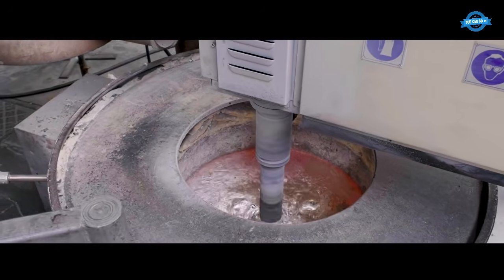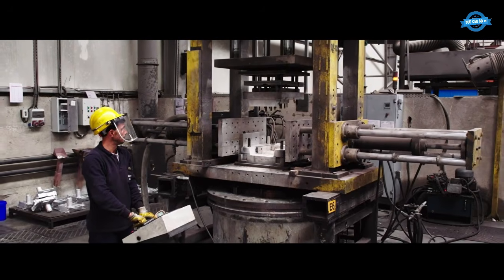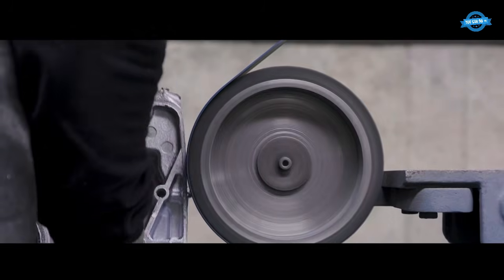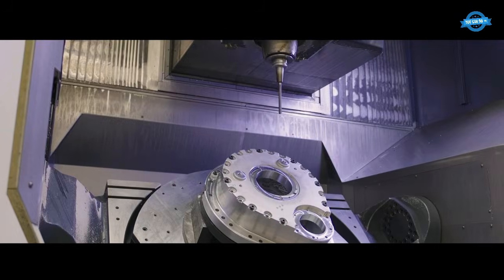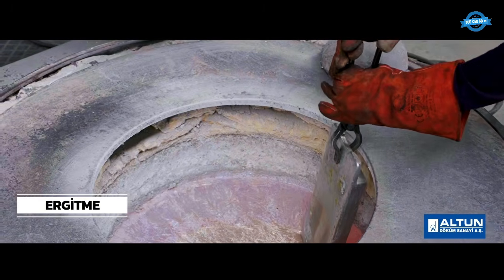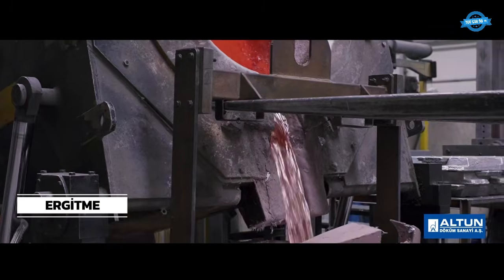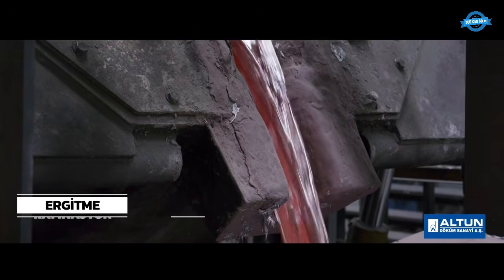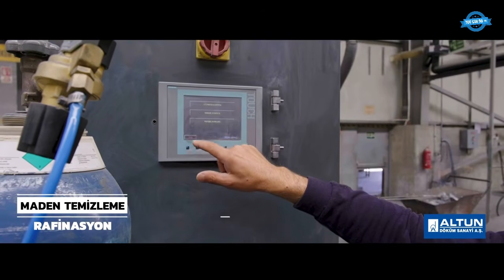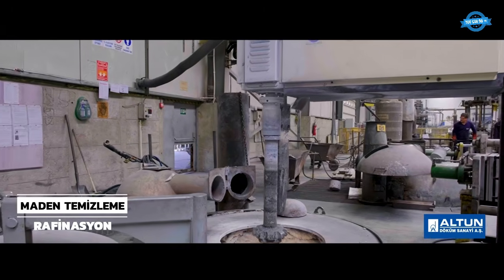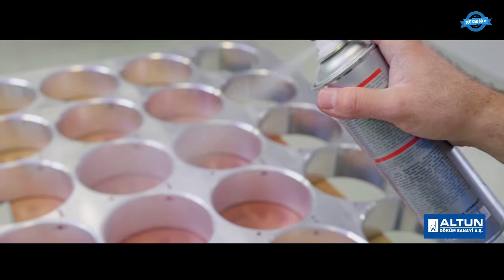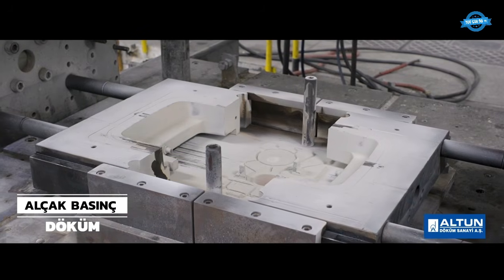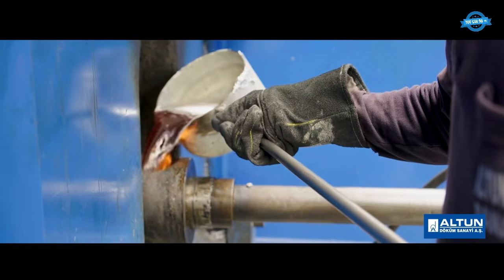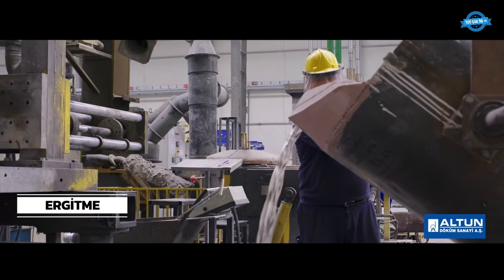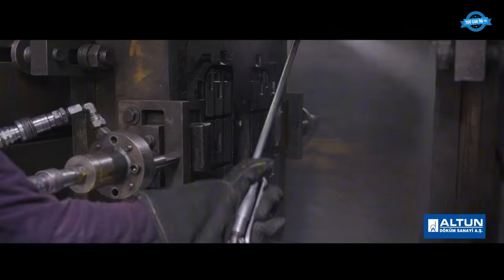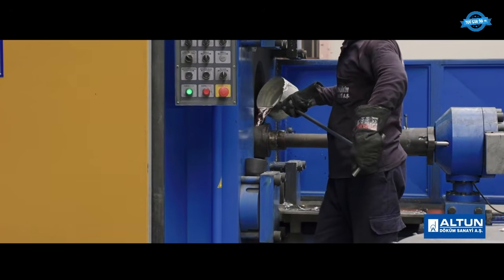Aluminum casting for the auto industry runs on completely different physics from steel. Lower melting point, faster cooling, higher sensitivity to gas absorption. An aluminum melt will happily pull hydrogen out of the surrounding air and turn your finished part into a porous mess of tiny voids. That is why every batch gets grain refining, modification, and degassing treatments in fully automatic machines before it ever sees the mold. Chill mold casting, low-pressure die casting, gravity tilt pouring, sand casting, the method gets chosen to match the specific geometry and mechanical demands of the part.